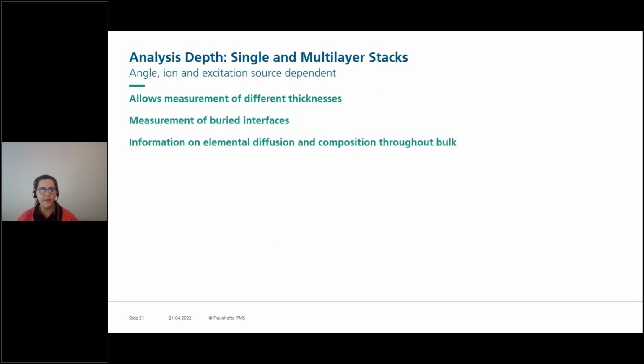There are several ways to do analysis depth with our instruments in order to look at single or multi-layer stacks. This allows the measurement of different thicknesses, it allows the measurement of buried interfaces, and it gives you information on elemental diffusion and composition throughout the bulk of your sample.